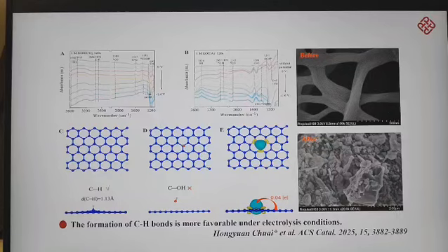Based on the above experiment results, we proposed the mechanism of the carbon reduction reaction. Graphitic carbon exists in sp2 hybridization with delocalized pi bonds in addition to carbon-carbon sigma bonds. When graphitic carbon is connected to the cathode, the carbon atoms carry a negative charge. Meanwhile, the hydrogen evolution reaction on the cathode produces a large number of active hydrogen species in the solution. The interaction between the negatively charged carbon atoms and the active hydrogen species disrupts the delocalized pi bonds of graphitic carbon, leading to the formation of hydrocarbon products.